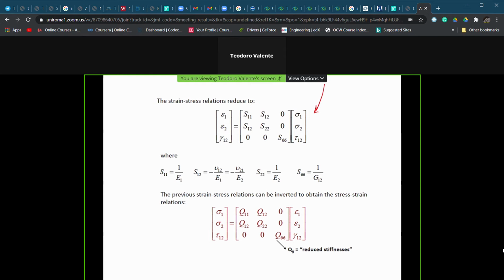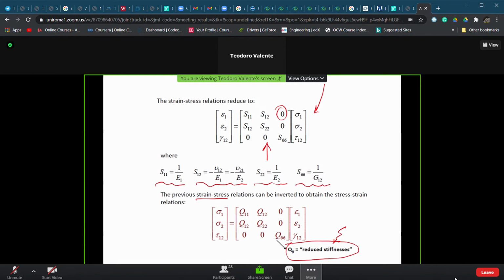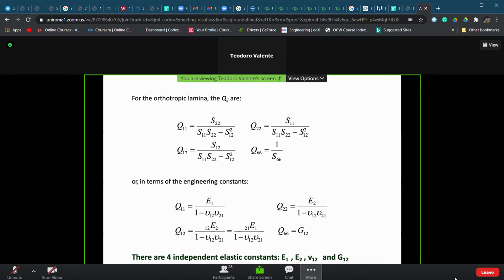this one, with no shear coupling effect again, in terms of the compliance matrix, which is derived from the previous expressions, the estimation of the values of the matrix itself. Or if you want to write it in the stress-strain relation, we usually use as notation the definition of the Qij matrix, which is also called the reduced stiffness. Why reduced stiffness? Because we have made the hypothesis of an in-plane stress state.